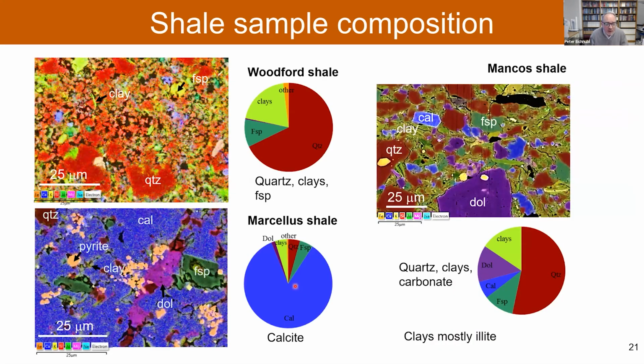And the shales vary quite a bit in composition. The Woodford shale sample that we got is very quartz rich. You see it's two thirds quartz, then feldspar and clays. The Marcellus is actually very calcite rich. It's almost a limestone. This particular sample has a lot of calcite in it. It's just the way it came, with some clays, of course, and some feldspar. And the Mancos is maybe somewhere in between. It has less quartz than the Woodford, and more carbonate, feldspar, and clays. The clays in all those cases are predominantly illite, with some kaolinite. In the Marcellus, it is purely illite. There is a little bit of smectite in the Mancos, but overall they are not smectite-rich shales.